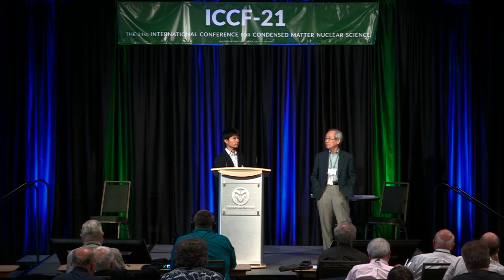Unfortunately, we haven't detected any gamma rays, but probably our detectors are cheap ones, so we are going to renew them to detect the energy spectrum of the gamma rays as well as neutrons, which is important. What I'm saying is you could measure this a couple of different ways. The other thing is to use a plastic panel, which has no resolution but large area. It would also respond to neutrons, so you don't really care what lights it up. But you could pull the foil after you're done with the experiment. It's got a 2.8 day half-life, and you can look at it with either sodium iodide or high purity germanium. All right, okay, thank you.